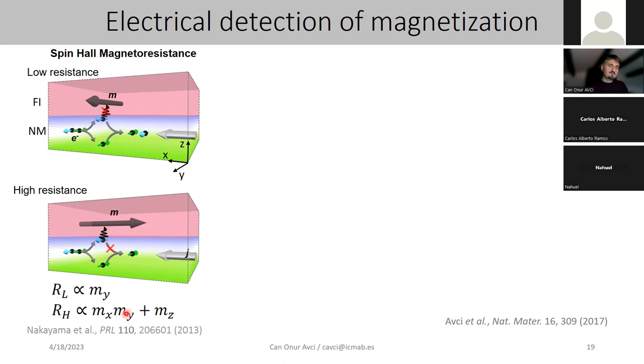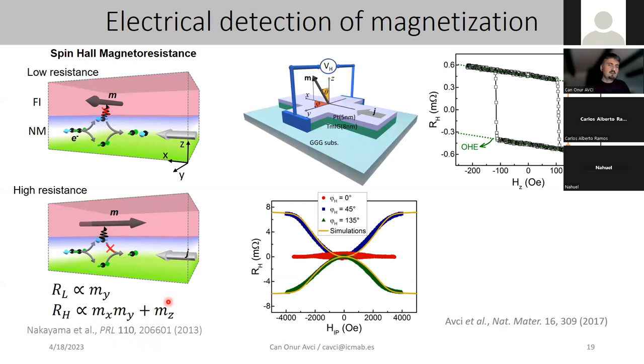In Hall effect measurements, because of this reflection and absorption phenomena, you have a signal proportional to the product of mx and my within this coordinate system. Plus, due to the precession of the spin current around the magnetization, you also get an additional signal that is proportional to the z component of the magnetization. That's exactly like in the metallic case, but now you also get some planar Hall and anomalous Hall-like behavior in the insulating case.